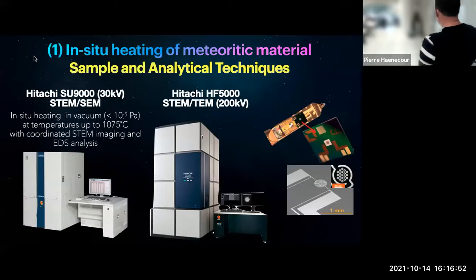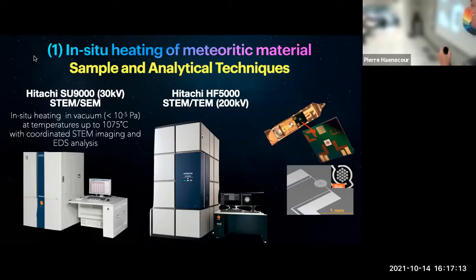In terms of instrument, you can see here how the basic heating holder works. You have a small heating chip with this silicon nitride film in the middle that's being heated, and the black is basically those holes. It's 30 micron holes, so we only heat very, very small particles. We want them to be as small as possible so we can look at them in a transmission electron microscope, so you can actually get information in transmission.